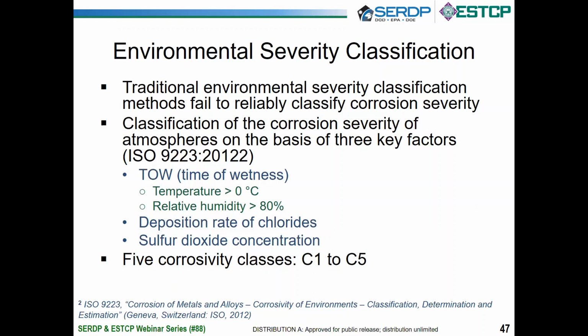We've collected data that shows you can have wetness events below this relative humidity, and that's all very closely related to the geometry of the corrosion that's going on, as well as the salt species that are present. And so a lot of what we want to be able to do is quantify the time of wetness and make a distinction about how this severity classification fails to accurately assess time of wetness. Slide 48, please.